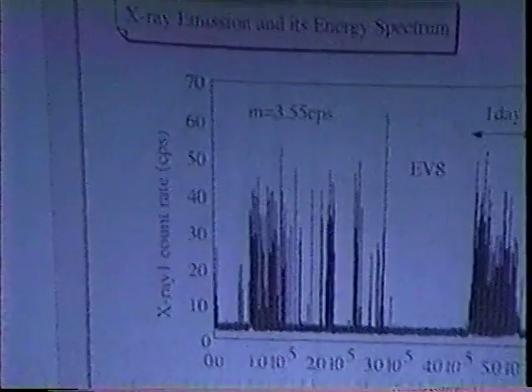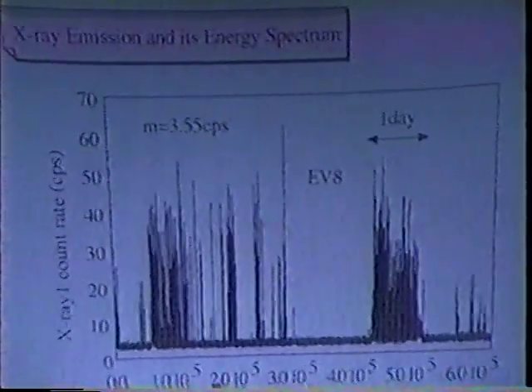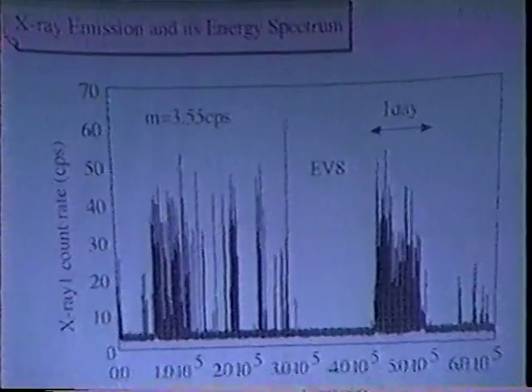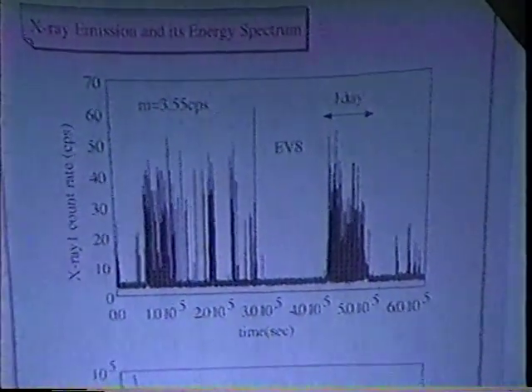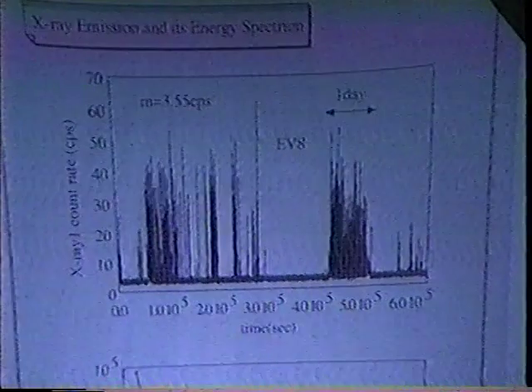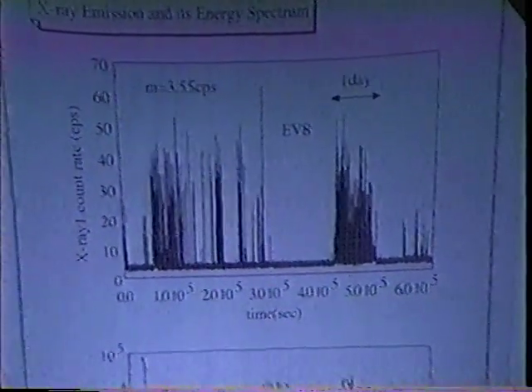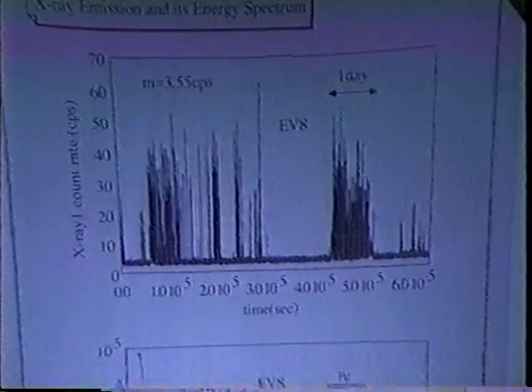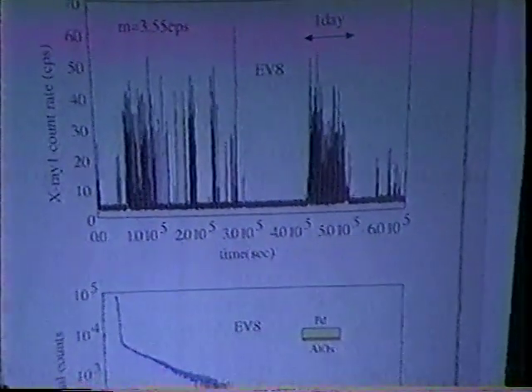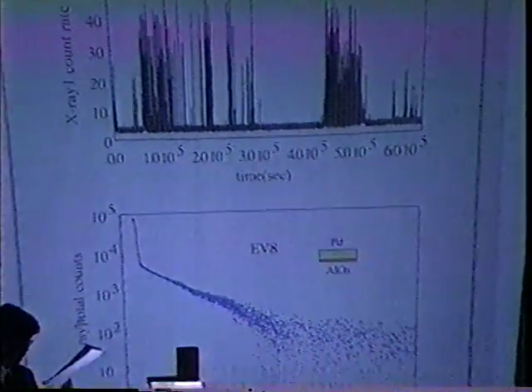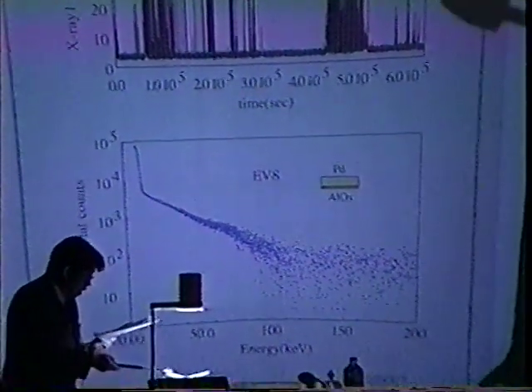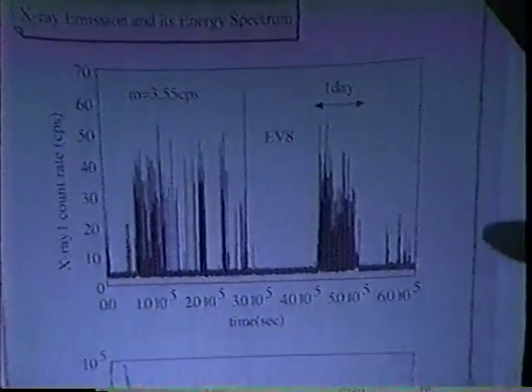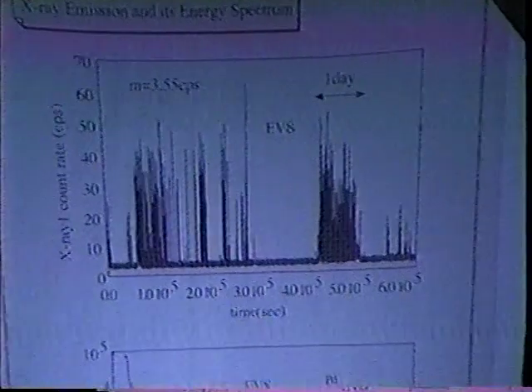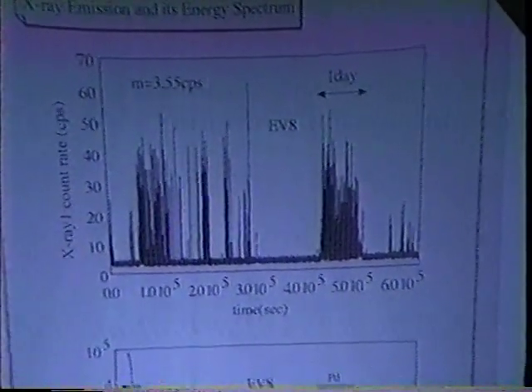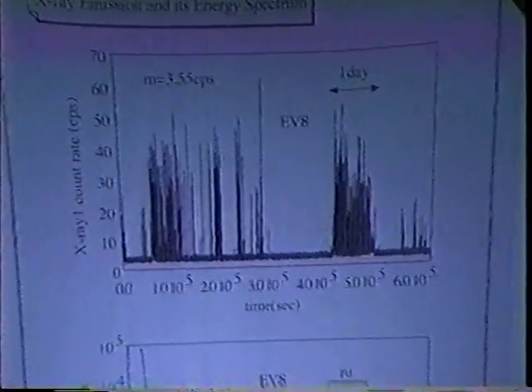Let's move on to the next point. This figure shows the example of X-ray emission and its energy spectrum. This sample has aluminum thin film on it, and this data was obtained by X-ray detector in the vacuum chamber. Upper figure indicates time evolution of X-ray. X-ray count rate reaches over 10 times larger than that of background, as you see.